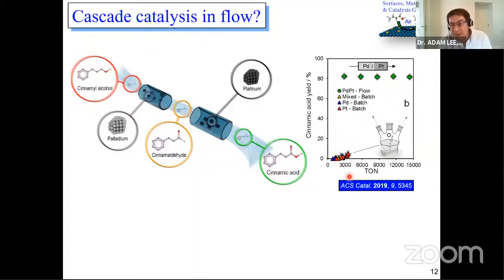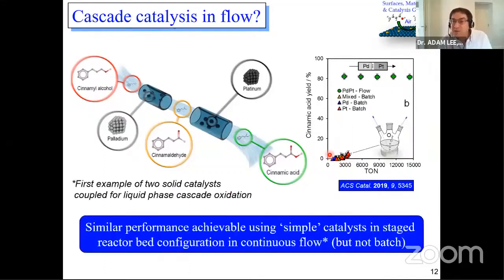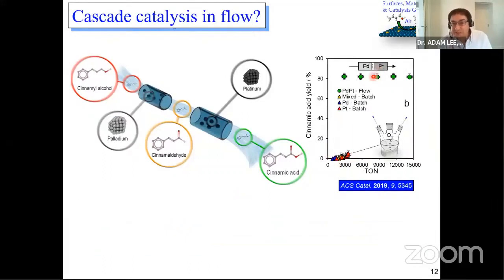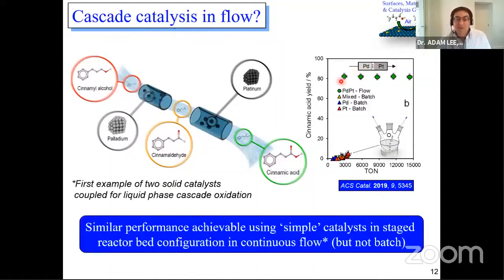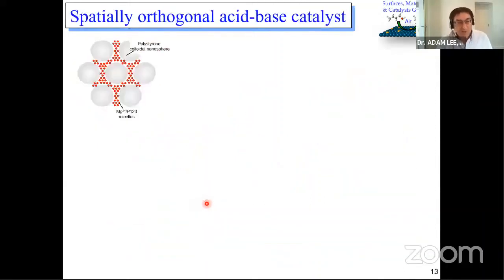And these systems are very stable. So if you look at the batch reactions, your turnover numbers, the activity of the catalyst, is quite low versus the flow reaction system. So both these two scenarios, having the catalysts coupled together in the same particle, spatially orthogonal, or put in direct sequence to each other in a flow reactor, allow you to get very high performance for cascade oxidations. We've since moved on to make an acid-base variant of those.